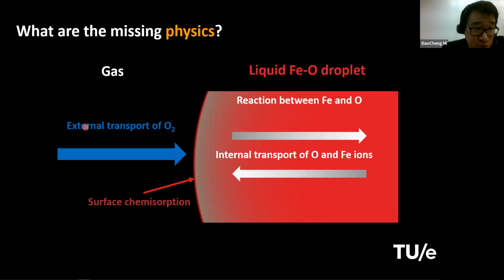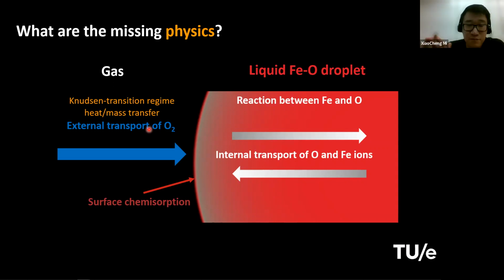Before, we had external transport, but modeled as continuum transport. But we know that at this very high temperature, the molecular mean free path of the gas can become larger. So the particle size may become more comparable to the mean free path, and the particle may end up being in a transition regime or free molecular regime of heat and mass transfer. That's number one. Number two is the surface chemisorption. Before, we assumed that all the gas molecules can be absorbed into the particle upon their collision with the particle surface, but there could be some accommodation limits, like maybe some of the oxygen molecules can just bounce back without being dissolved into the particle.